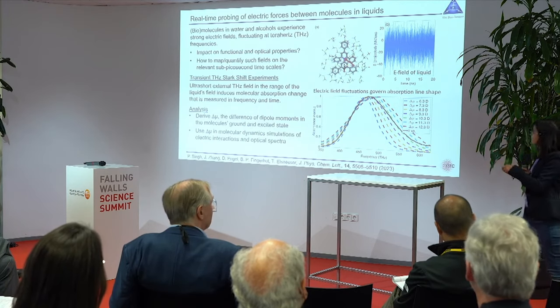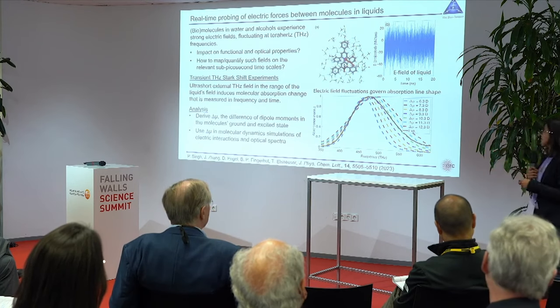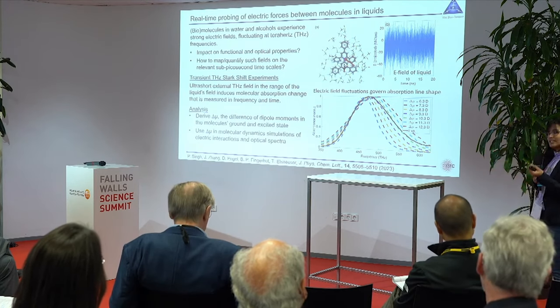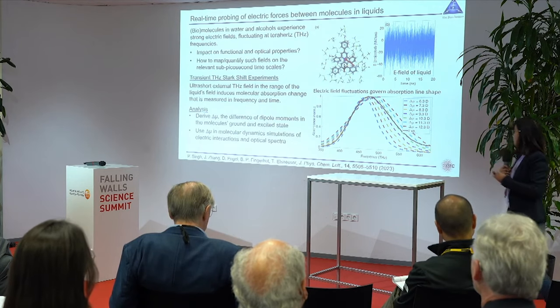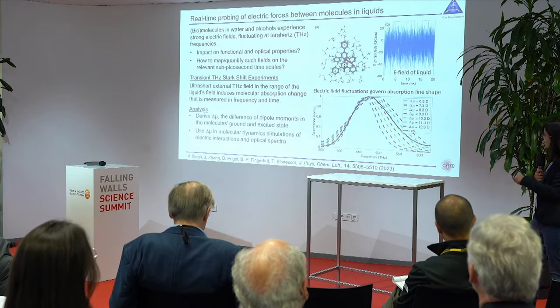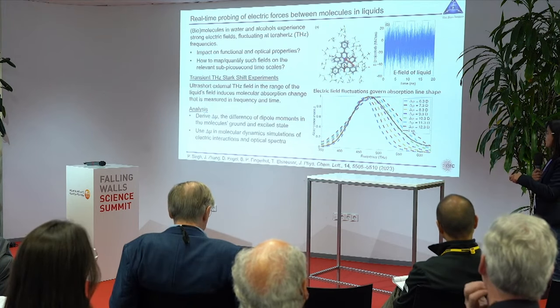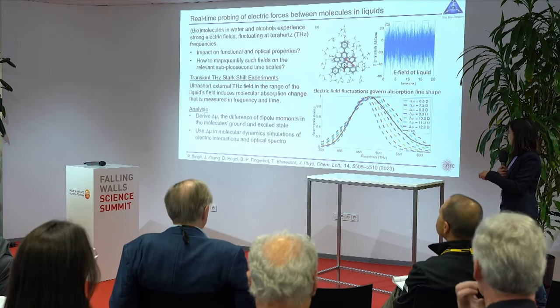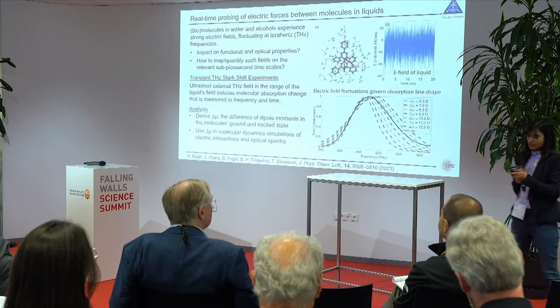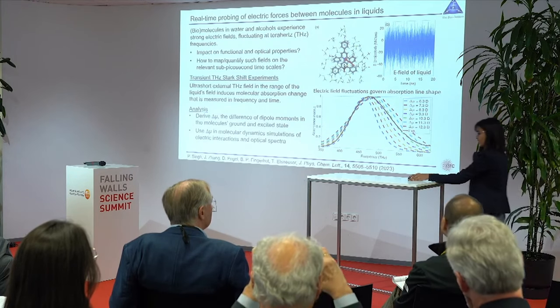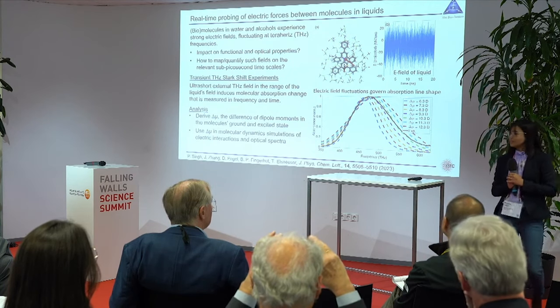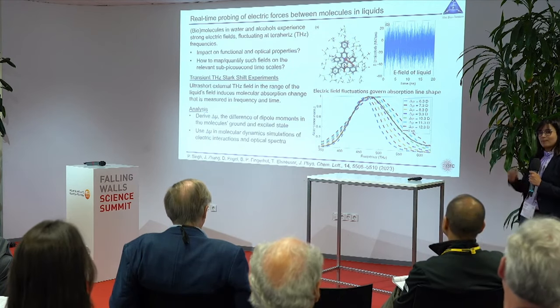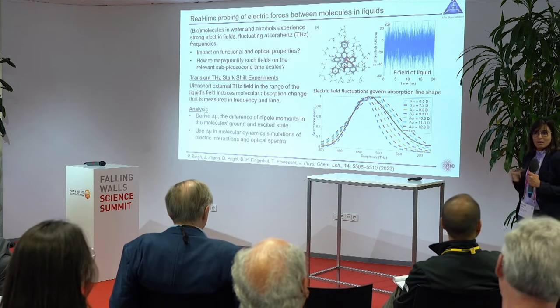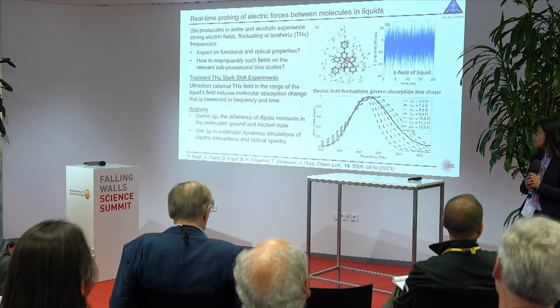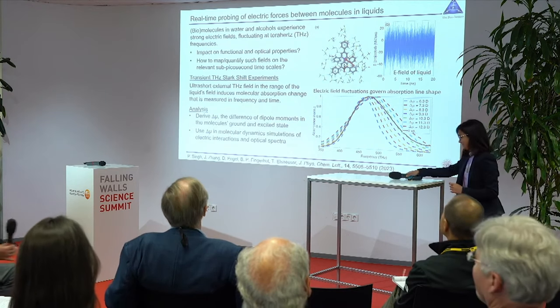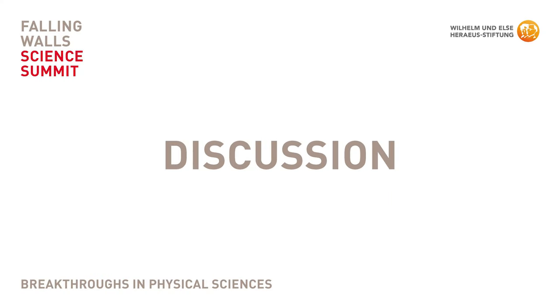So we simulate the electronic absorption spectrum based on this mechanism and the experimentally derived delta mu values, or the dipole difference values. And we see that our electronic absorption spectrum closely matches the theoretical values. So the potential of this method is already shown using this scheme here. And at the moment, we are applying this system to more complex systems such as biomolecules. Thank you. Thanks to all of you.